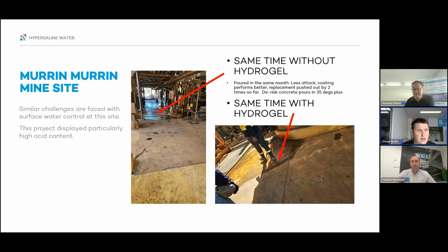So they switched across about 5 years ago to the hydrogel admixture. They also spray applied a hydrogel curing treatment, and then carried on and did the epoxy coating following that. What's really interesting is you can see in the right-hand picture, just below where the arrow's pointing, a crack. Normally, once the chemicals got through the membrane and into that crack, you would start to see the damage in that left-hand picture. With the hydrogels, because it stops the acid and chemicals going past that very top surface and stops them spreading horizontally into the concrete matrix, you get a lot better service life out of that concrete. So that damage mechanism that you would normally see isn't happening in that environment.